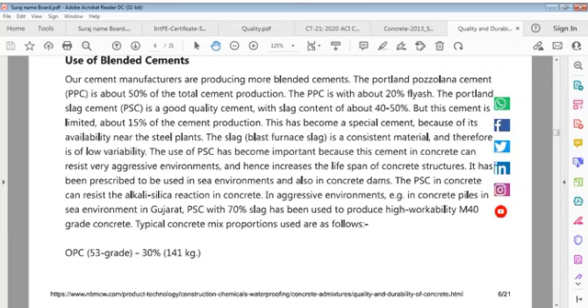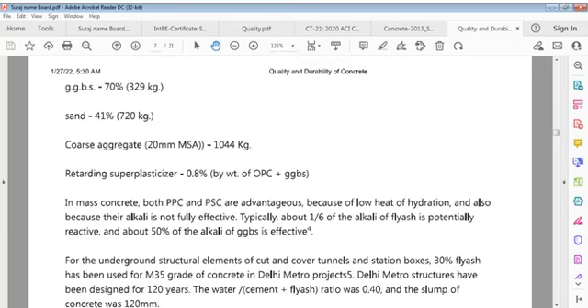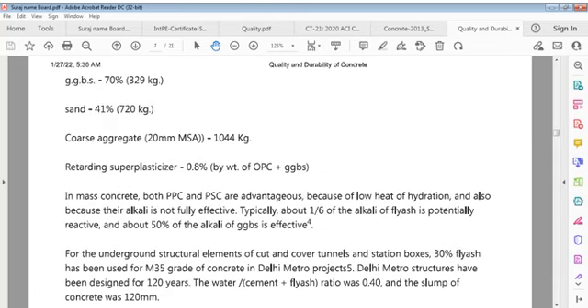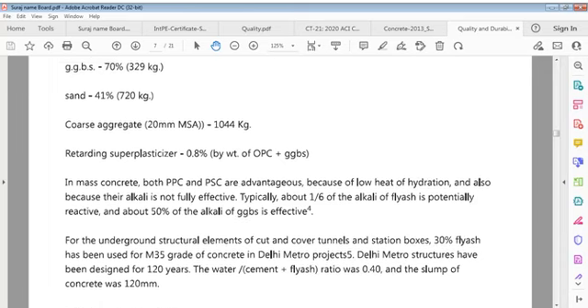The pile concrete mix proportions used are as follows. GGBS 70%, 329 kg, sand 41%, 720 kg, coarse aggregate 20 mm MSA, 1044 kg, retarding superplasticizer 0.8% by weight of OPC and GGBS.